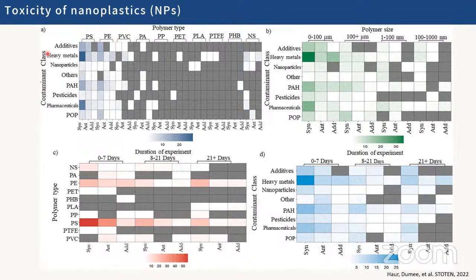Now, what we can do, however, is still identify these polymers and class the types of co-contaminants we have in that case. And it has been shown, for instance, that heavy metals, especially in ocean and wastewater, are able to nucleate as metal oxides or metal structures onto the surface of a number of them, including polystyrene, PE, and PVC, for instance. And that's a big concern, because you can imagine how the uptaking of microplastics in fish, for instance, could be challenging for the fish digestion system. But if now that microplastic is saturated with metal, you have another level of complexity, obviously.